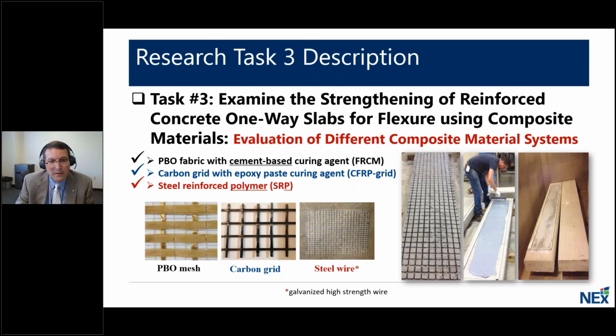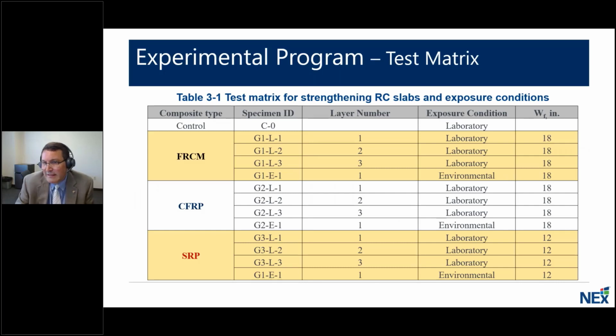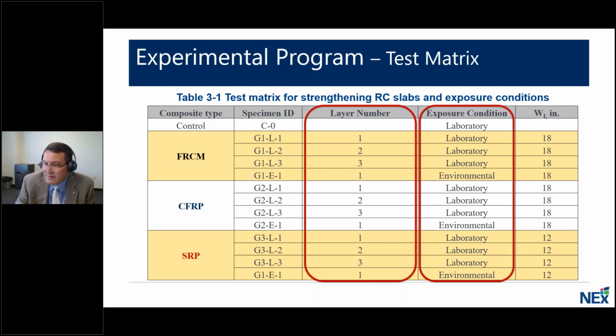In case you're wondering, why would I put this material close to the soffit where corrosion might be an issue if the material matrix is very permeable to moisture. The variables we looked at in this phase of work looked at the number of layers, so 1, 2, 3, and one layer was done in the environmental chamber for looking at durability. The exposure condition, as mentioned, so either the lab or in the environmental chamber, as you saw earlier, and then also the reinforcement ratio to try to keep the expected load carrying capacity relatively similar.